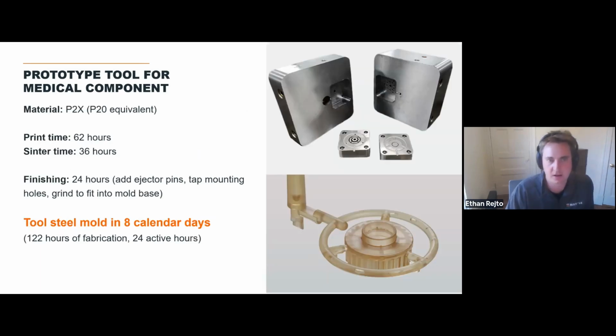Example here, printed these in 62 hours, about a day and a half in the furnace, finishing about 24 hours on these inserts. That was adding the ejector pins, tapping the mounting holes, and just grinding it to fit into the mold base. So pretty consistent finishing required for these inserts, but ultimately it was mold inserts in just 8 calendar days. They estimate, so 122 hours of fabrication, but only 24 hours of active hours, which is obviously very important to save their toolmaker time here.